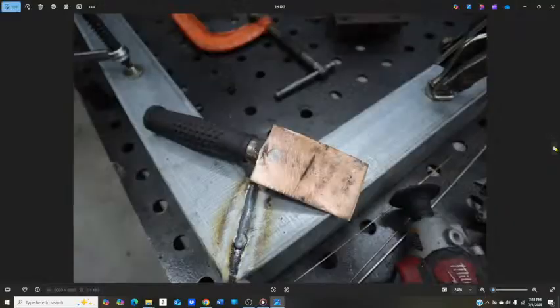I was talking to Rick a couple weeks ago, and this is a really handy tool for welding sheet metal. This is a piece of copper with a handle on it. This actually came from Harbor Freight, but you can do all kinds of different stuff with this. With copper, you can buy a copper block or copper bar stock, and you can clamp it or weld it, or mount it to the backing of where you want to weld something, and you can weld against it, and the weld will not absorb or penetrate the copper. You can see here there's a little line. This is where I had a piece of sheet metal sitting on here, and I welded it, and that's the residue coming out of the copper, but there's no penetration.